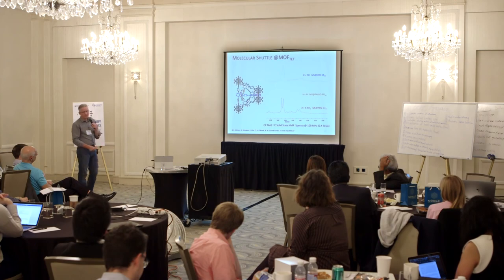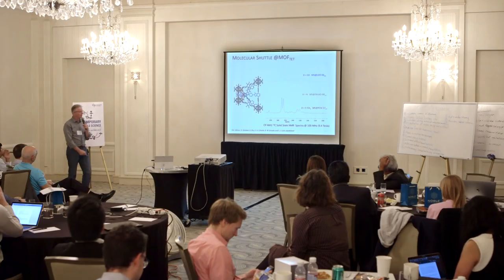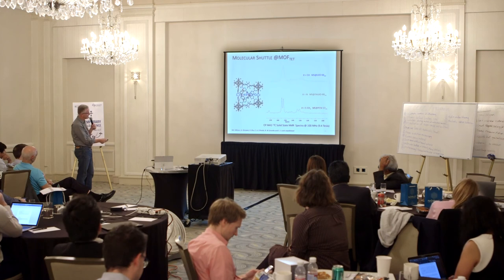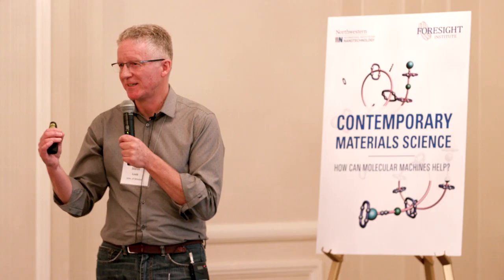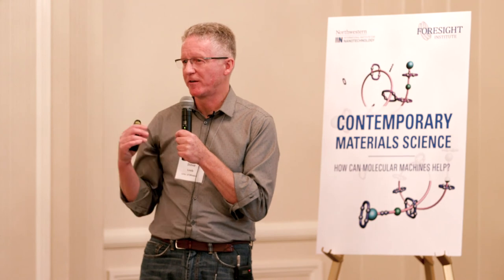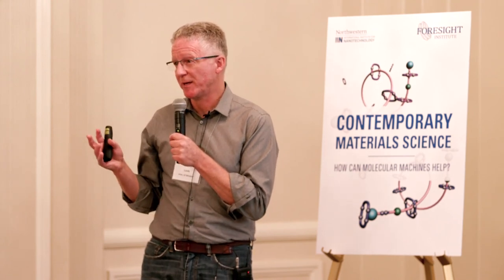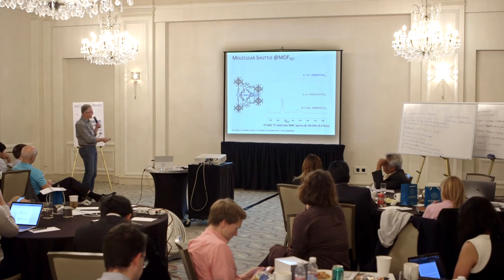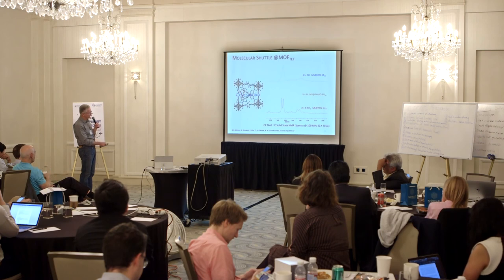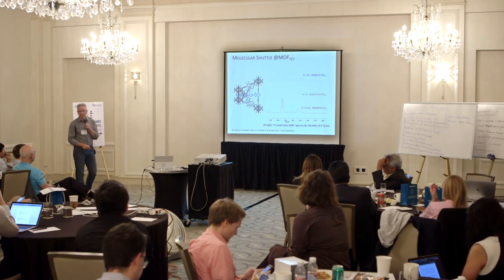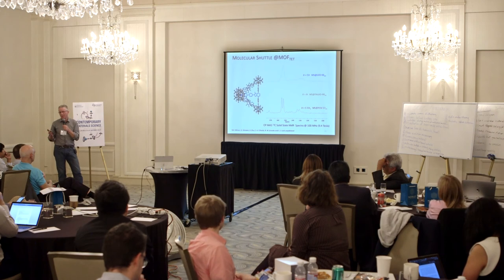So it turns out that when these other groups on these other linkers are methyl groups, you get two peaks. And you get two peaks at every single temperature, which is a bit disappointing because that means nothing's moving, right? If you look closely at this structure, you can see it. If I was to put this in space filling, it is pretty clear that those methyl groups are blocking that ring. So it's a really fine line, right? There's not too much steric crowding because I can make the material. I wouldn't be able to make it if it was too sterically crowded, but it's too sterically crowded to push by that methyl. And because that ring wants to be pointing into that cavity, there's not much I can do about that. So what we did was we figured, let's make one where the opposite would be true.